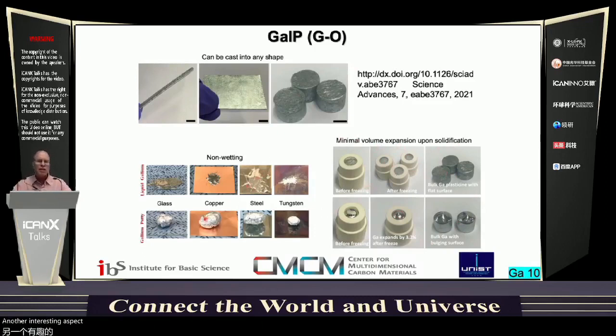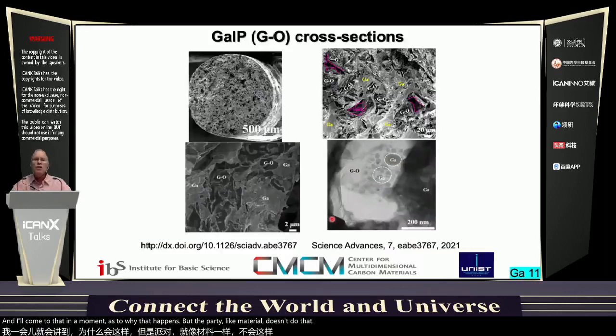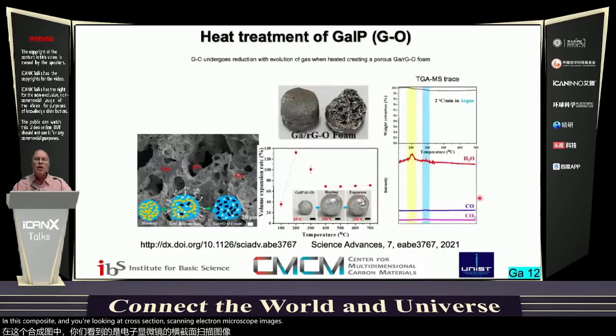Another interesting aspect is that, as I mentioned, gallium can amalgamate with certain metals, and then it also tends to leave this kind of stain on glass and other materials. And I'll come to that in a moment as to why that happens, but the putty-like material doesn't do that. So in the cross-section, we can actually identify the presence of graphene oxide or stacked graphene oxide sheets in this composite, and you're looking at cross-section scanning electron microscope images. And another thing that Chunhui did that I thought was quite clever, we heated the gallium with graphene oxide or graphite oxide present inside it.